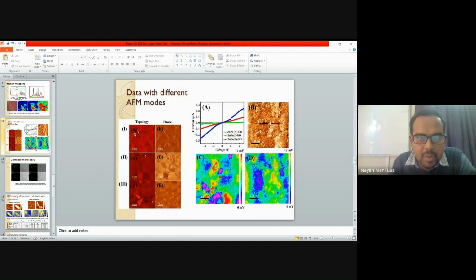So we also did the AFM topography and phase characterization, where we can see that the interactions between the graphene oxide and the ZnPc were very high when it is heated. The naming AB: A is for your topography and B is for your phase. Phase basically gives the mechanical interactions between the two composite layers. You can see when it is in J aggregate, they don't have very distinctive interactions, but when it is in H aggregate form, they have very distinctive interactions, which ascertain the good interactions between these two composite materials.